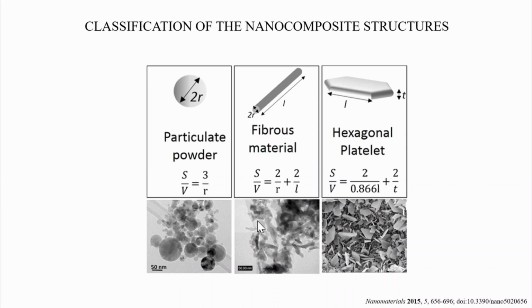The next one is fibers or tubes having a diameter less than 100 nanometers and an aspect ratio of more than 100. And the last one, plate-like nanofillers, which can be layered materials with typically a thickness of the order of 1 nanometer and an aspect ratio in the other two directions of at least 25. The surface area to volume ratio for the different types of reinforcement is displayed in the same figure.